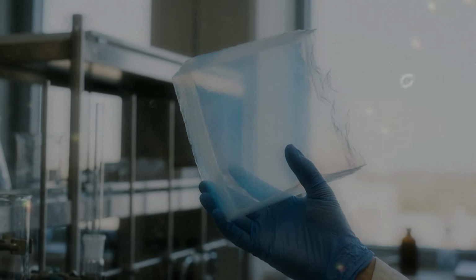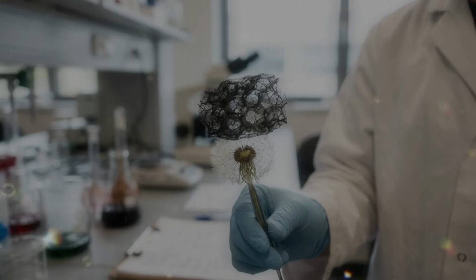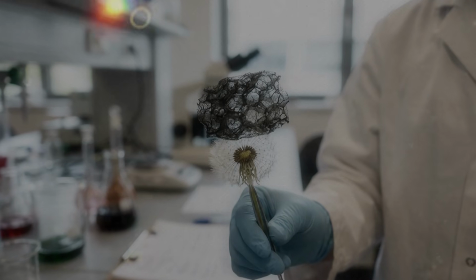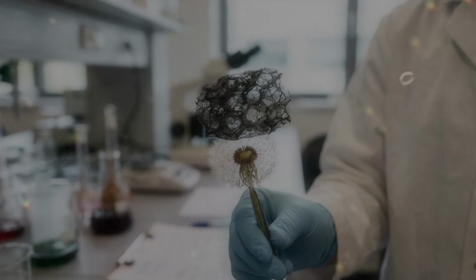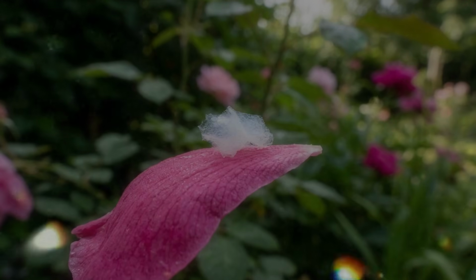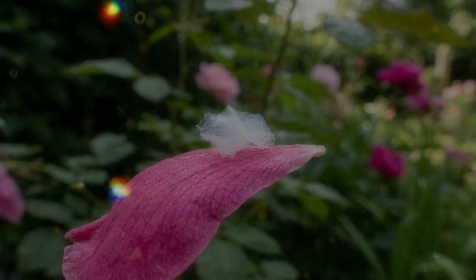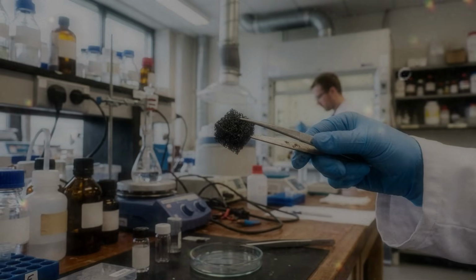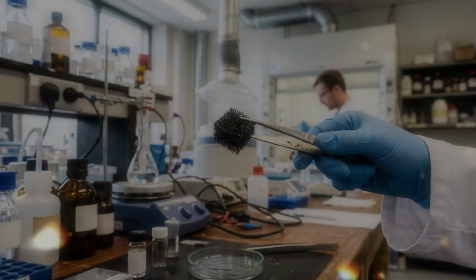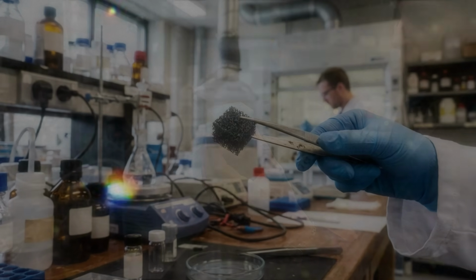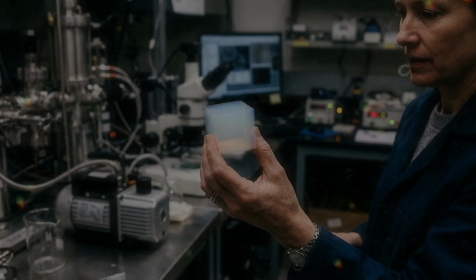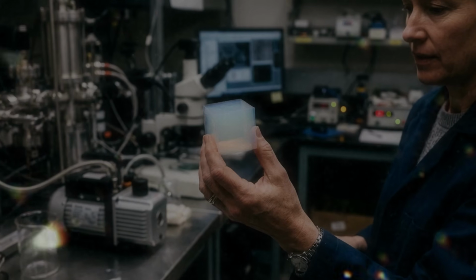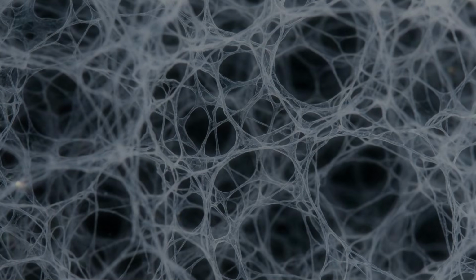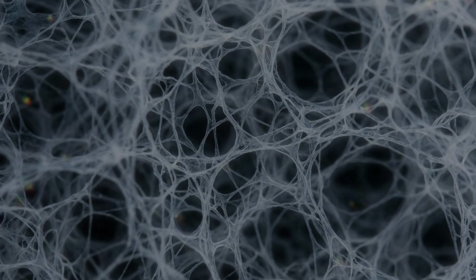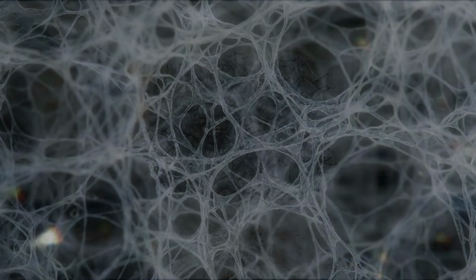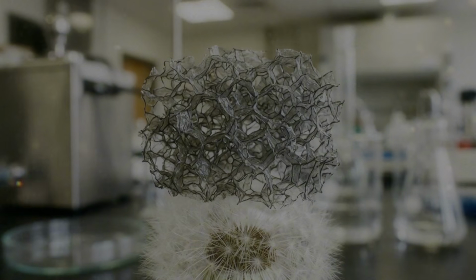The pores that reduce weight also create an advantage. They give liquids and gases access to the conductive surface. In a dense piece of carbon, most of the atoms remain buried. In an aerogel, a large portion of the carbon sits beside open space. This is important in energy storage. A battery or capacitor depends on the movement of electrical charge and charged particles. Electrons travel through the solid electrode. Charged particles move through a liquid or solid electrolyte. Useful storage occurs where these routes meet. Graphene aerogel can provide a connected path for electrons, while its pores allow the electrolyte to enter.